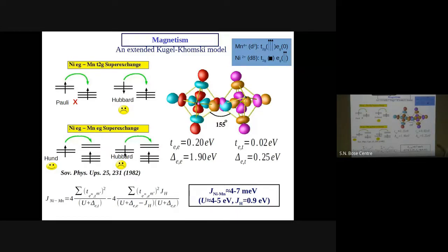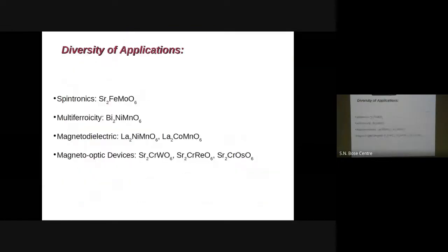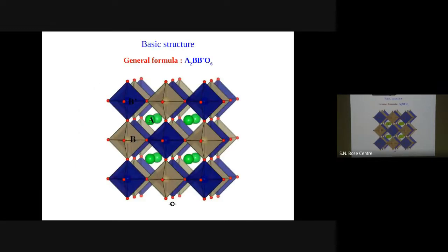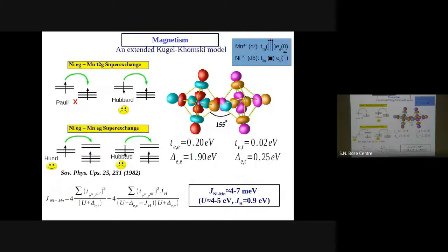Now, you know the shapes of t2g, which are like dxy, xz, yz, while eg are x square minus y square and 3z square. In principle, there cannot be any interaction between the t2g and eg if the angle between manganese, oxygen, and nickel is perfectly straight. Because if you remember the structure, the superexchange path will be like this. It has to go from one metal site, B site, to B prime site via oxygen. If it was perfectly cubic, this angle would have been 180 degrees, and in this case your t2g-eg interaction will be disallowed. But as it so happens, because of the distortion, this angle is pretty distorted. Instead of 180 degrees, it is 155 degrees. As a result, t2g-eg hopping is still allowed, although the magnitude is smaller.